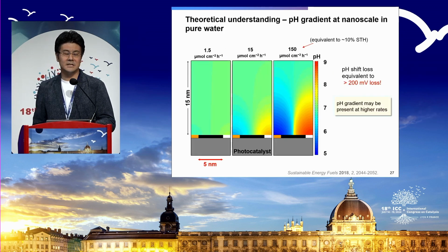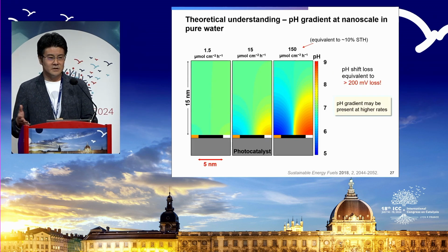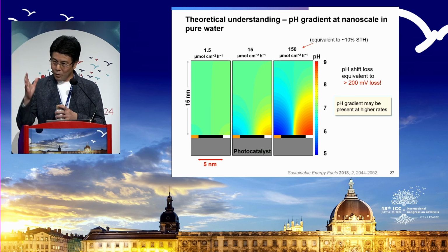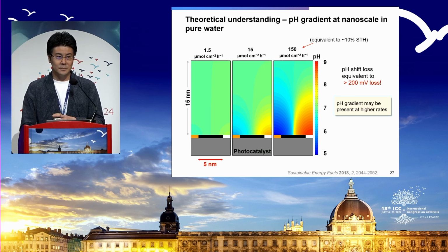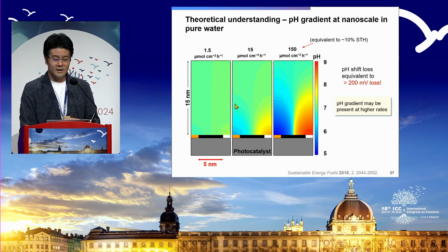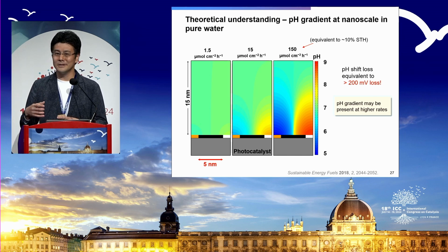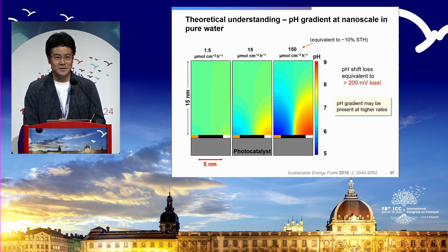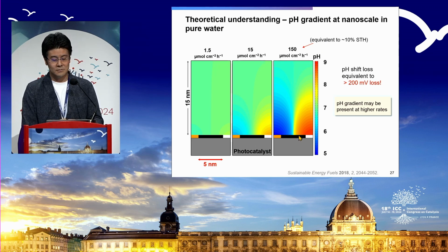But the next one is the pH gradient. Of course, we need to assume many things. So if we have a completely static condition, where ions don't move, but we start to generate oxygen evolution and hydrogen evolution, you start to develop this pH gradient at the steady state. When you are working at low current density, or in this case, say, poor photocatalytic performance, you don't change pH, of course. But if you're really serious about achieving 10% solar-to-hydrogen efficiency, you start to see a complete pH gradient shift. And this shift is around pH 4.